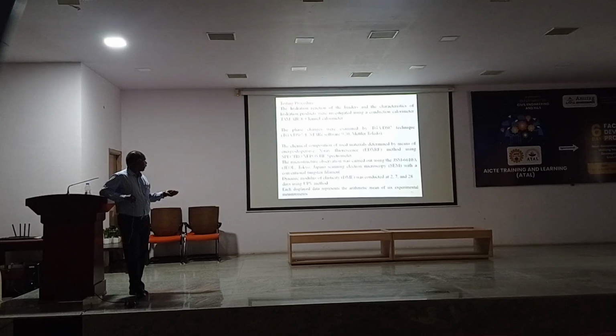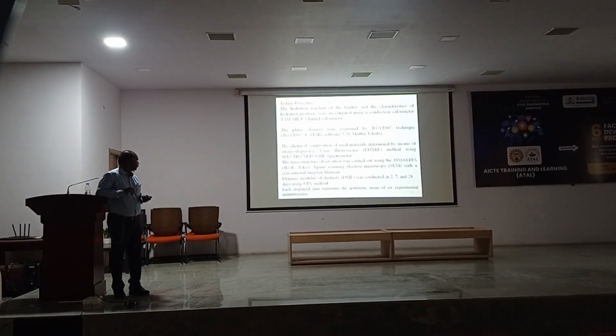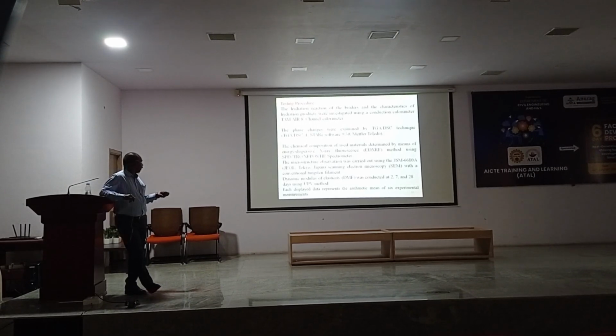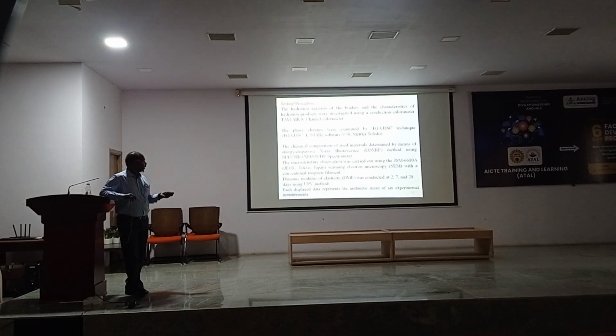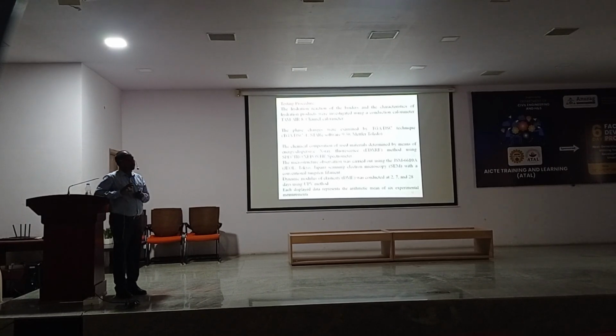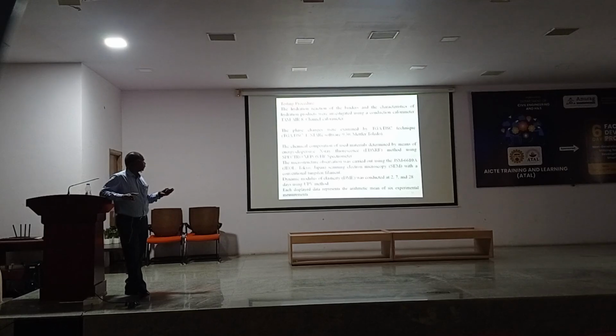This is already discussed here. XRF is used for finding the chemical composition. Some microstructure studies are also there, but I am not including this microstructure analysis. And SEM is also there. Dynamic modulus of elasticity was conducted at 2, 7, 28 days by using the ultrasonic pulse velocity test. For each data point we are testing 6 samples.